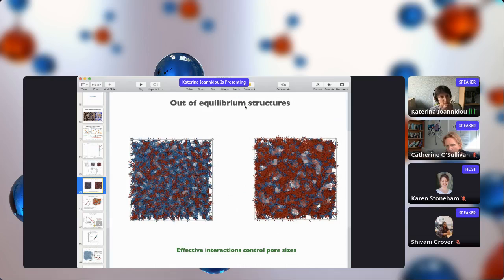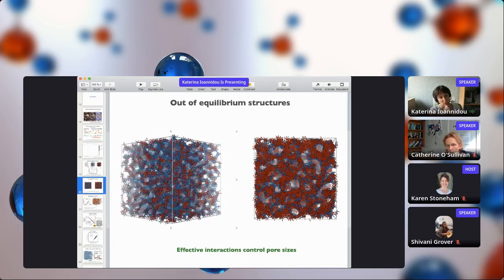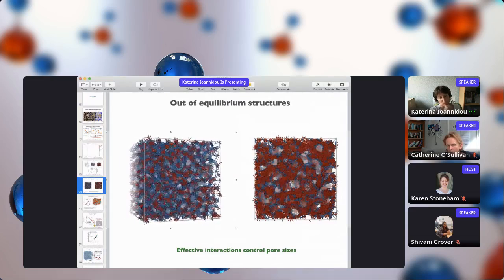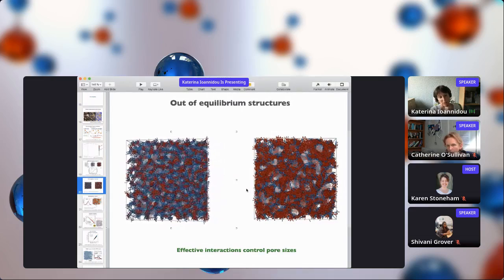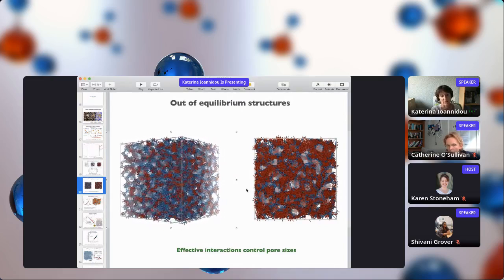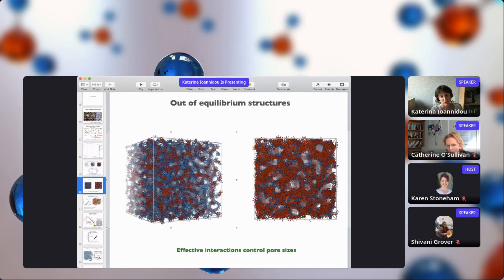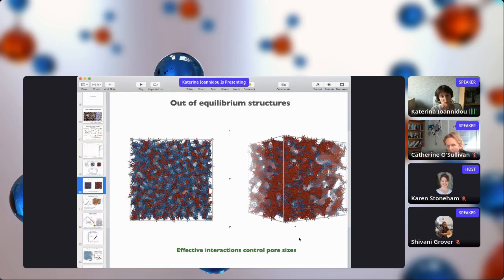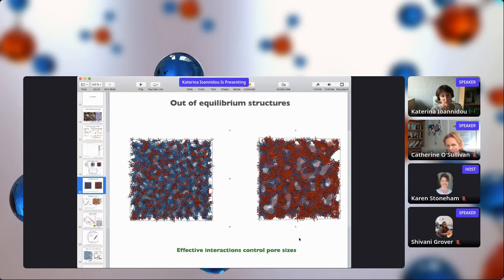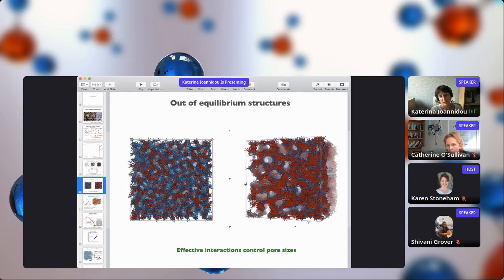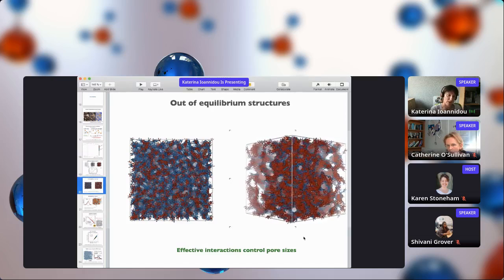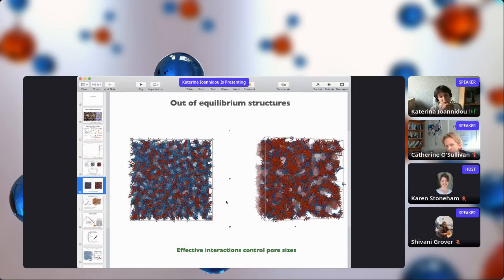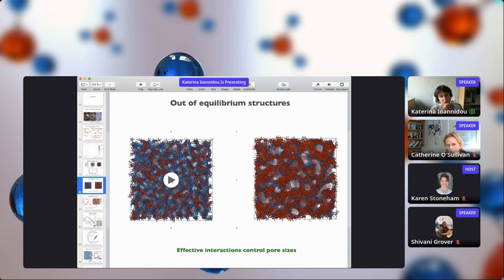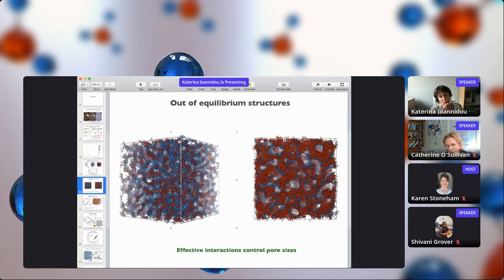Another point is that we can have these structures that are out of equilibrium and porous. These structures can have different porosity controlled basically by the degree of attraction and repulsion in the system. These two systems are done with the same simulation protocol, at the same volume fraction. The only difference is that here we have an attractive well which is stronger than the repulsion, whereas in the other case, when the repulsion is stronger, we can stabilize smaller pores in the system.